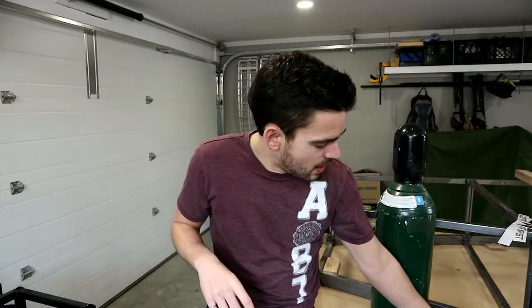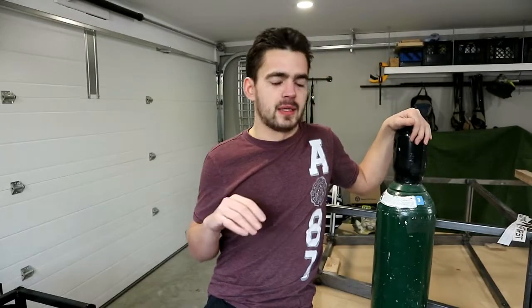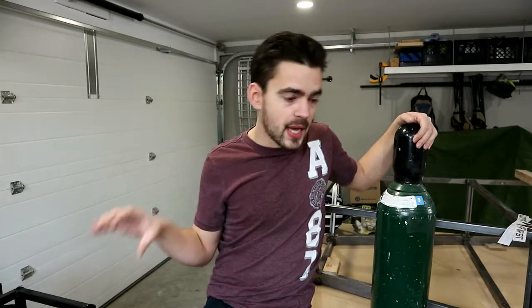But when we changed to a new bottle of gas, oh boy, it was way easier. All the welds were smooth. They were like that nice, shiny, metallic. They were great. The gray was gone. The porosity was gone. The pepper flaking was gone. It was great. So clearly I had bad gas. It's contaminated with either another gas or with moisture or something.